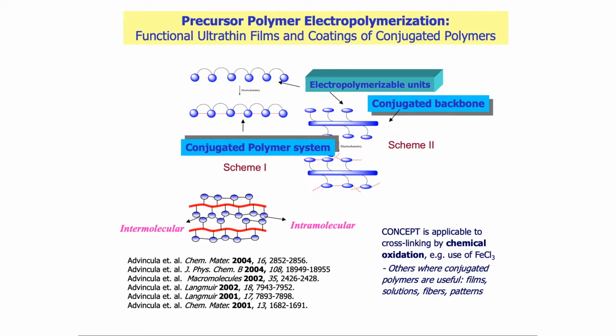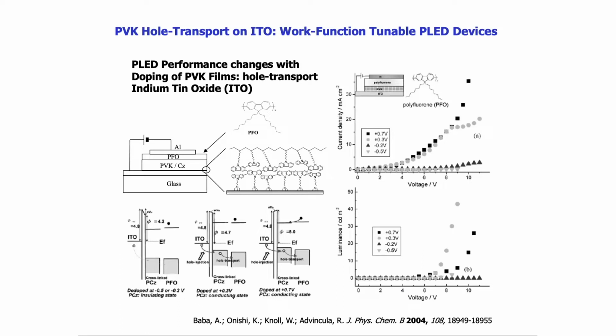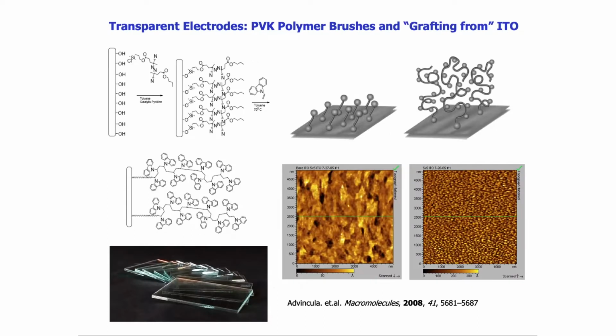So for example, we can take polyvinyl carbazole and cross-link it at the indium tin oxide surface to enable the formation of an LED diode with polyfluorene as shown here, where the cross-linking of the PVK and the oxidation state can control their efficiency or even turn-on voltage. So what I'm talking about is pictorially depicted here. Indium tin oxide is a transparent conducting substrate.